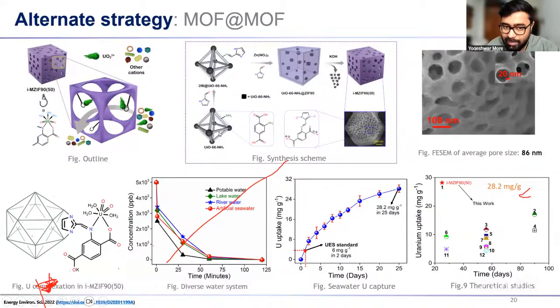So we made first an acid stable MOF, which is base non-stable. UiO is base non-stable but acid stable. We did acid-base chemistry. We functionalized it with another linker. We form a ZIF, which is base stable but acid unstable. And now we use the base to remove the base unstable MOF. So UiO was base unstable. So we removed the base unstable MOF in the alkaline solution. So only the base stable MOF is left over. That is the ZIF-90-50. This is the chemical name of the MOF, and it has a porous structure. Why the selective porous structure? Because inside there were crystals. So from a crystal, we have removed the crystals selectively, and now we got this porous structure.